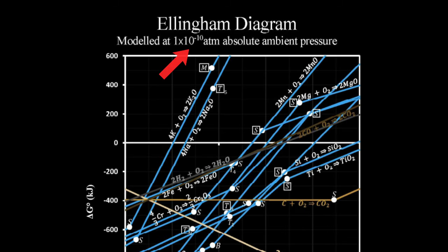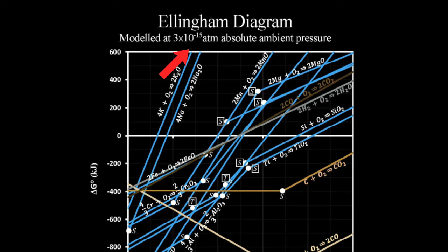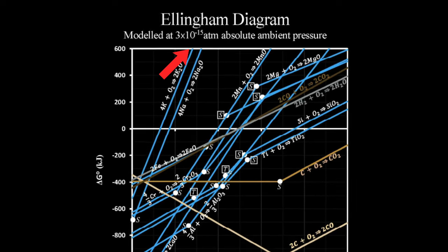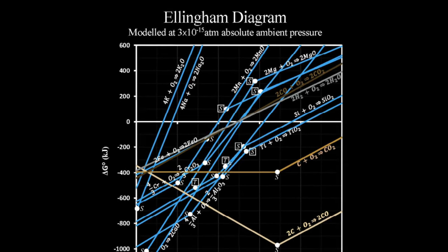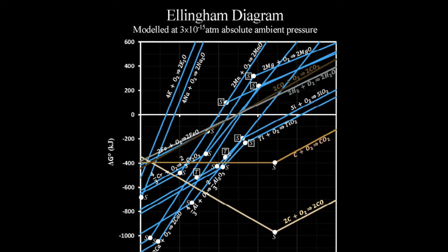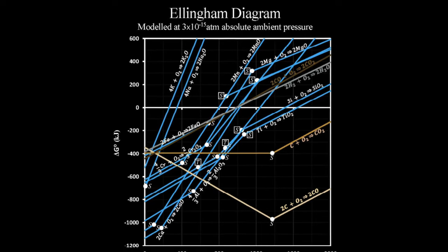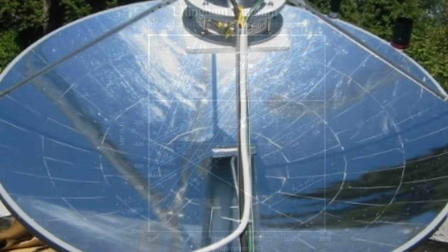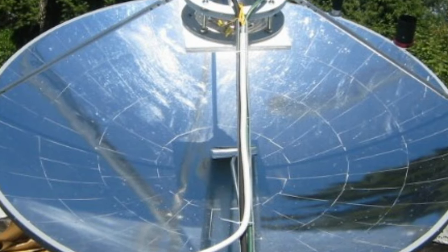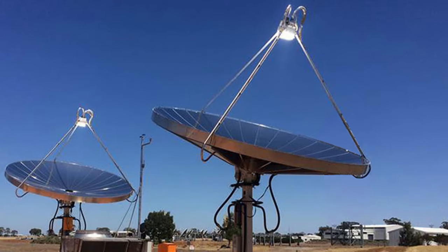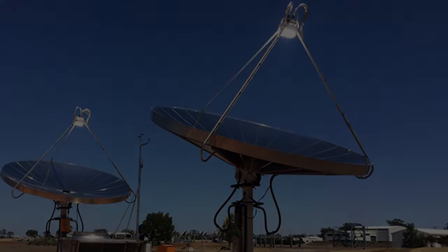And this isn't even the lowest vacuum diagram. This is 10 to the power of negative 10 atmospheres, while this chart, 10 to the negative 15, represents the pristine lunar environment. So the sublimation temperatures can actually be even lower, but it's not like that even makes much of a difference anyway, considering solar concentrators can reach temperatures of up to 5,500 degrees Celsius, the temperature of the sun's surface. Could this really be? Could we really just vaporize regolith at this temp and then distill the constituent elements individually?